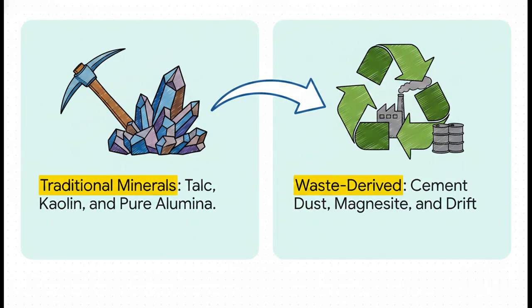Knowing the chemistry is one thing, but how do manufacturers actually make this stuff at a massive commercial scale? Well, making Cordierite requires a very specific mix of raw materials. Traditionally, engineers blend naturally occurring minerals, talc to get magnesia, kaolin clay for silica and alumina, and refined pure alumina powders. But here is the really brilliant part. Modern research is proving we can actually synthesize high-performance Cordierite from hazardous industrial waste. No joke, we're talking about using bypass cement dust, magnesite, and drift sands as alternative waste precursors. It's this ingenious zero-waste circular economy approach. We are quite literally turning industrial trash into a highly valuable, high-tech engineering ceramic.